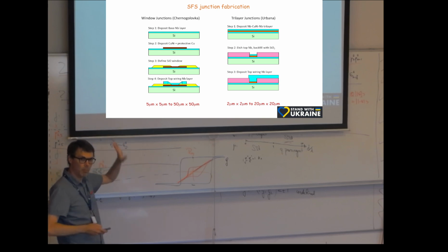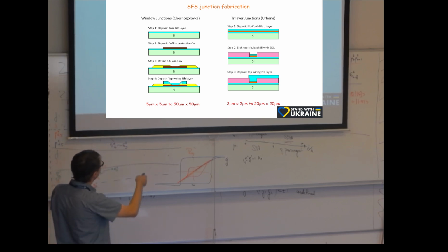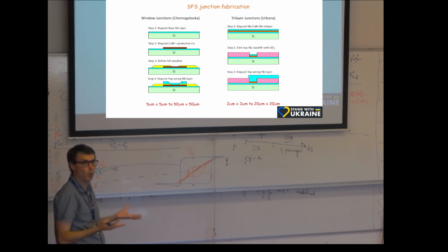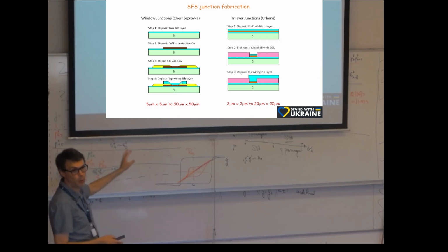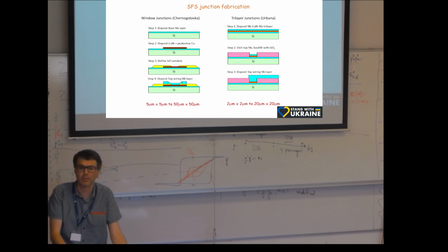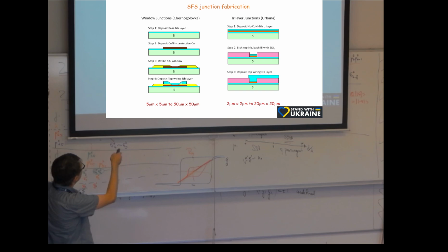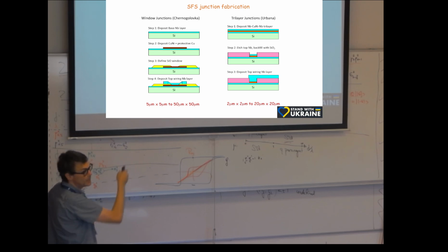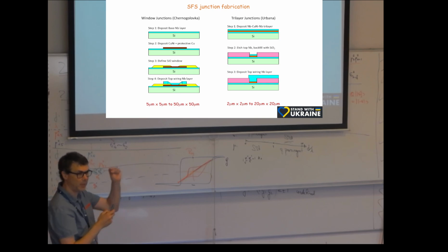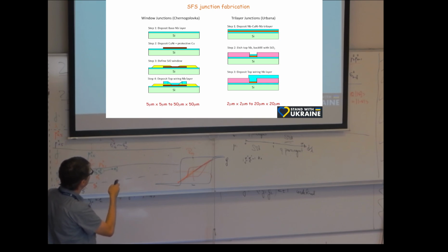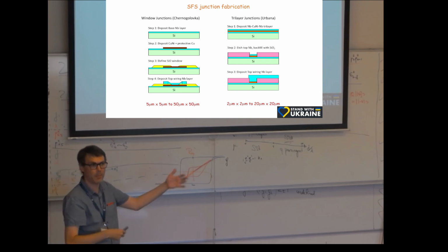I will show you more of these kinds of samples as we go along, but basically you start with something that is just a wafer, a holder of your device. In this case, it played no role other than just to be a table, a substrate for the junction. And then put a layer of superconducting niobium. Niobium is just a metal that becomes superconducting at about 9 or 10 Kelvin. Then you have to put the ferromagnet, which in this case is copper nickel. It's nickel diluted with copper. Pure nickel is too strong to be made this thin. And you can see this niobium is everywhere. This copper nickel is patterned. So there is a process for patterning called lithography.